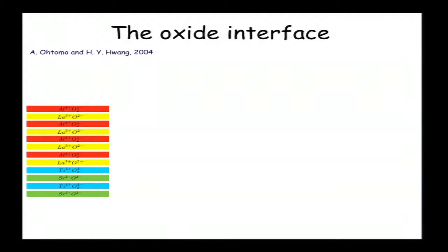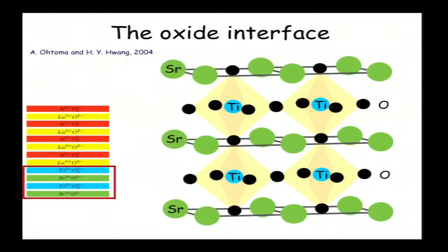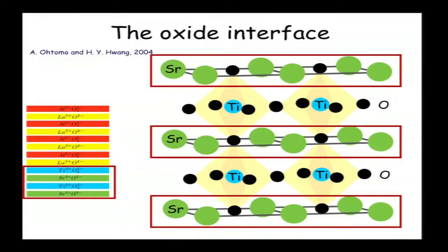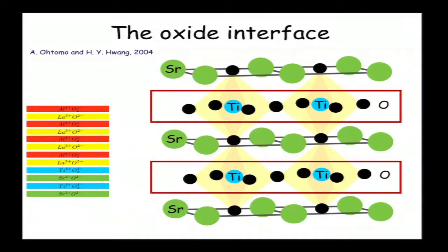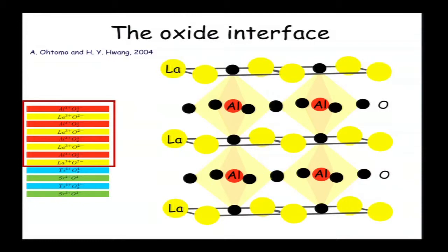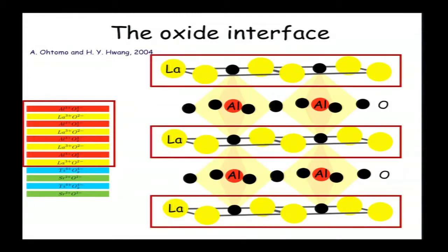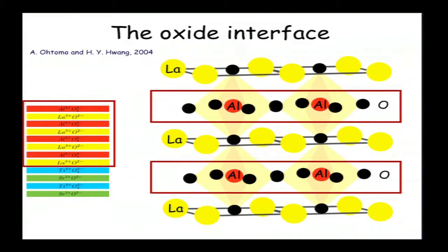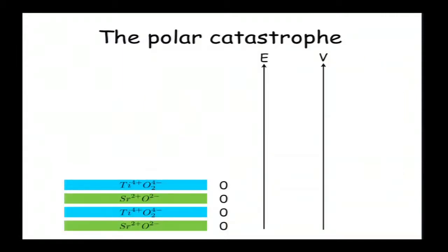Now, to understand this material, and what happens at the interface, we need first to look at each material separately. So let's look at strontium titanate. It has a very complicated structure, but what is important to us is that it has alternating layers of strontium and oxygen, and titanium and oxygen. If we look at the lanthanum aluminate, it has a very similar structure, but now the alternating layers are layers of lanthanum and oxygen, and layers of aluminum and oxygen. Let's look at what happens when we start with strontium titanate and grow layer by layer of lanthanum aluminate on top of it.